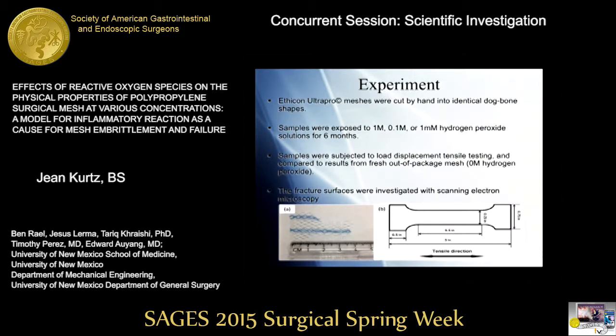After load displacement tensile testing, these samples were examined using scanning electron microscopy. And specifically, we were looking at the fracture surfaces. That's where the material snaps to see inside the fibers.